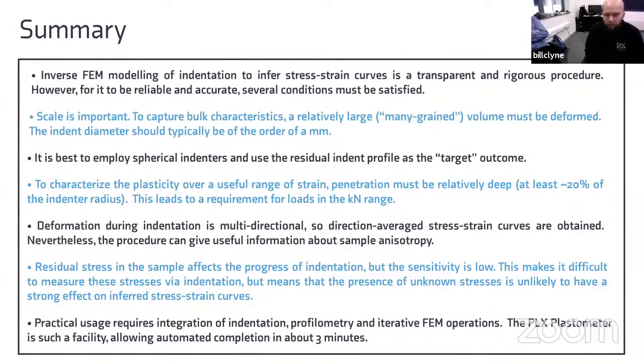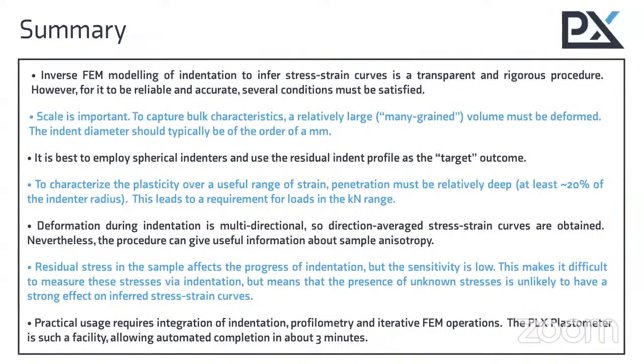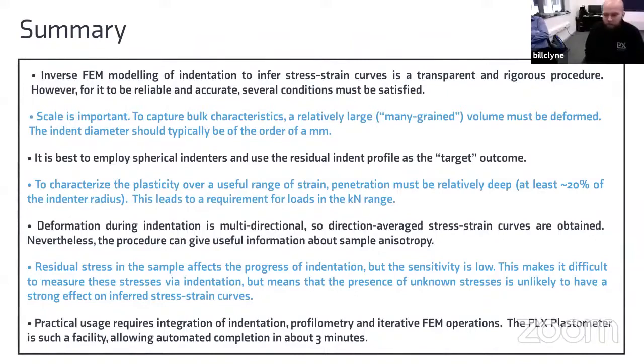First, as Bill outlined, is the scale. To ensure that the bulk characteristics are captured rather than just those in a single grain where the properties are highly anisotropic, and we don't actually capture all of the properties, such as the influence of grain boundaries. We must ensure that the diameter is large enough, typically of the order of a few millimeters, to make sure all of the microstructural features are captured.